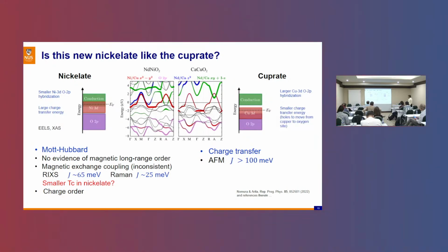And from RIXS, for example, we do notice some kind of magnetic excitations, but there is no long-range order, and the coupling energy is much lower than what we have in the cuprate. So this, again, is maybe something that has to be clarified, whether this has something to do with, for example, the lower Tc that we have. And then there are reports on charge order that have been proposed by different groups. But again, here there is an inconsistency that needs to be further clarified.